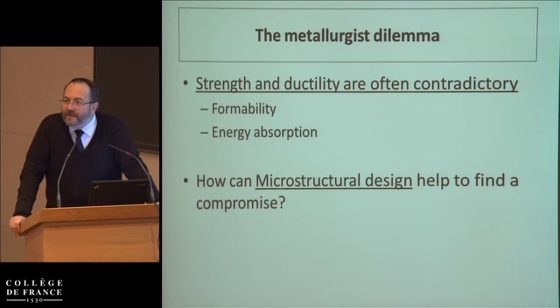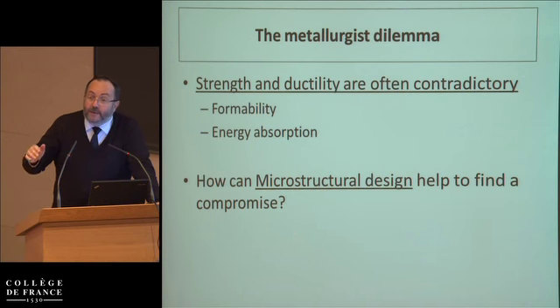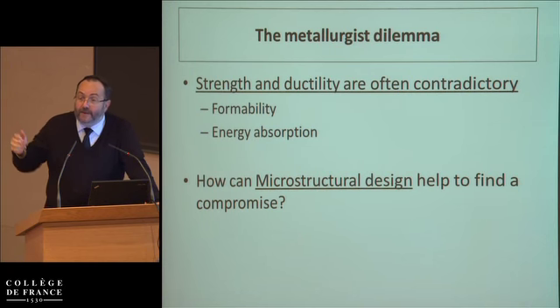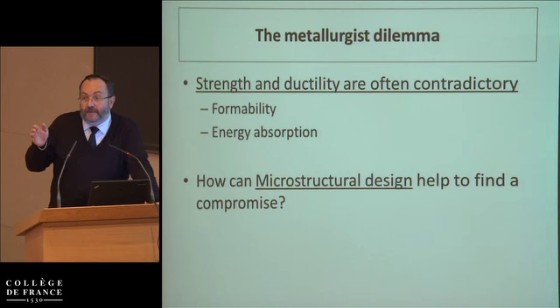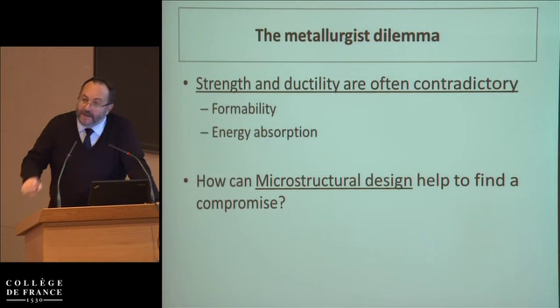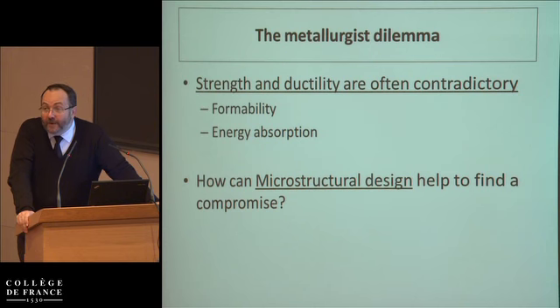When you look at the plastic deformation of a material which has some plasticity, you have the yield stress, which tells you when you start to plastify, and of course, when the material starts to plastify, its stiffness becomes lower. The increase in stress to get an increased strain is smaller than what you have in the elastic regime, and this is called the work hardening.